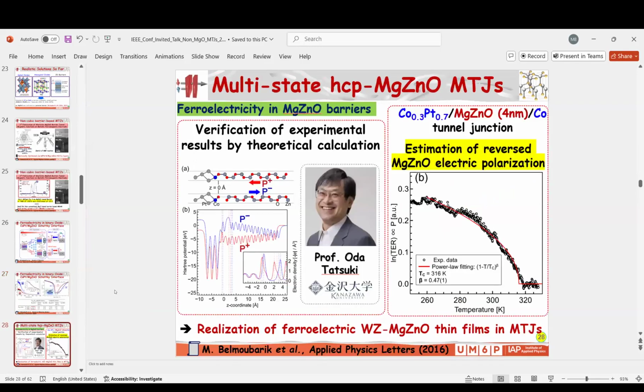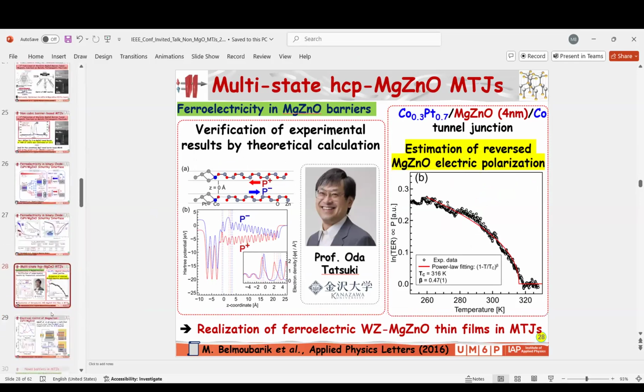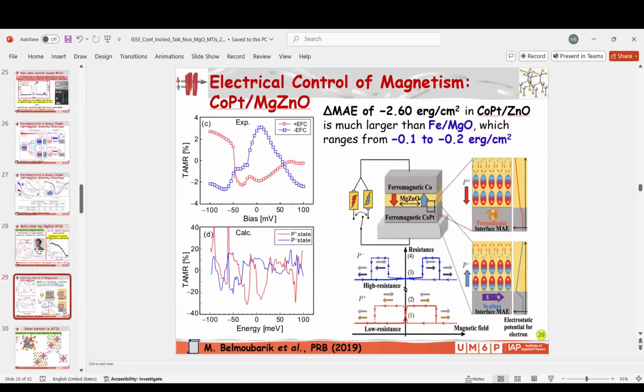We also confirmed this by theoretical calculation, and as I mentioned before, the temperature dependence of the reversed electric polarization shows here the Curie temperature of the ferroelectricity. So we realized a ferroelectric wurtzite magnesium zinc oxide thin film in MTJs, but this is one of the rare examples in MTJs. Later on, this is also very, very interesting: we use this ferroelectricity to modulate the magnetic anisotropy of cobalt platinum.